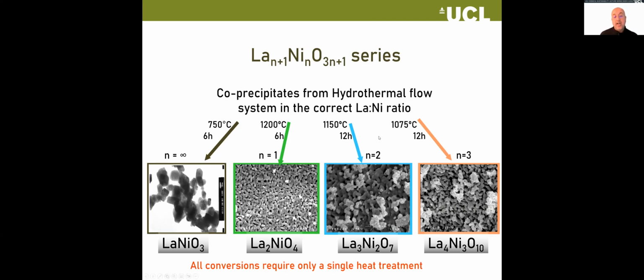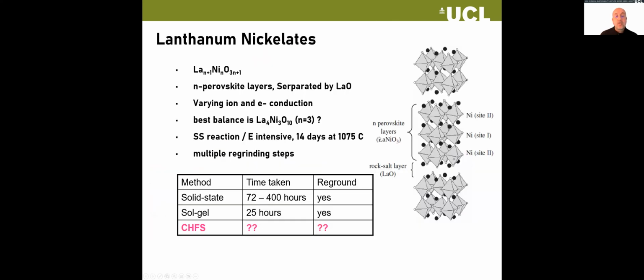Now, some of these are taking 12 hours. And the reason they take 12 hours without any grinding is that if you look at the structures of some of these lanthanum nickelates, they're quite complex, actually. They require quite a lot of organization. So in the first few hours, what's going on is some sort of structural reorganization. And eventually you see a very sudden change to the crystal structure. In the past, we even went to the beamline to try to identify when this change occurs and how fast it occurs. And it occurs between measurements.